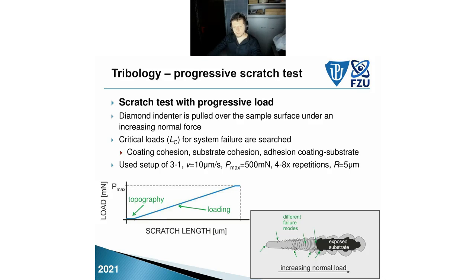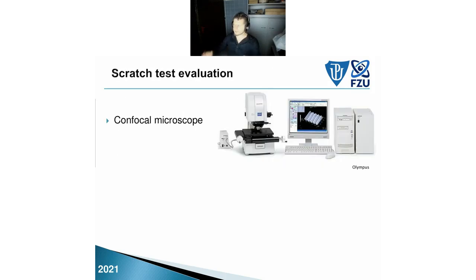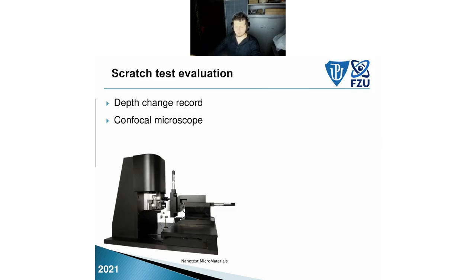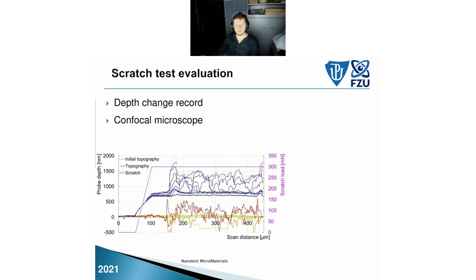We have used progressive scratch tests, the standard scratch test from zero to maximum load, and analyzed it using different techniques. In standard practice, when you analyze tribological properties during scratch tests, pin on disk, and several other tribological tests, you use optical evaluation. We also use a confocal microscope, which gives a little better resolution than a normal white light microscope. Here are some pictures. We more importantly use the depth change record from the nanotest itself to evaluate the cracks or delamination of the coatings, the jumps in the depth.